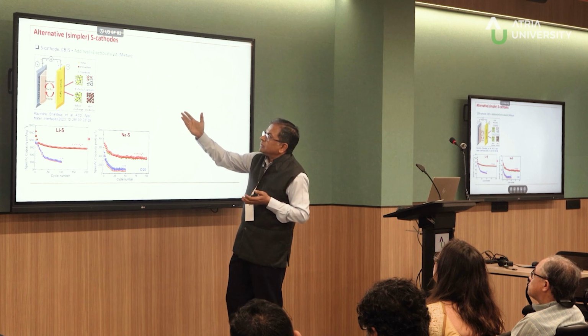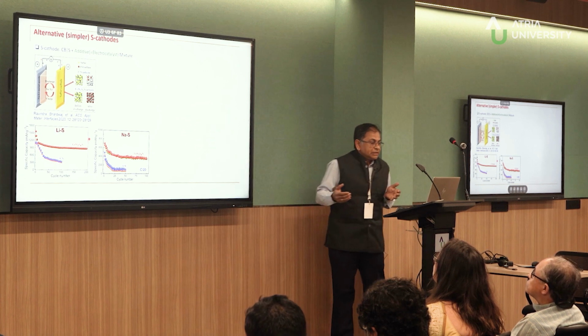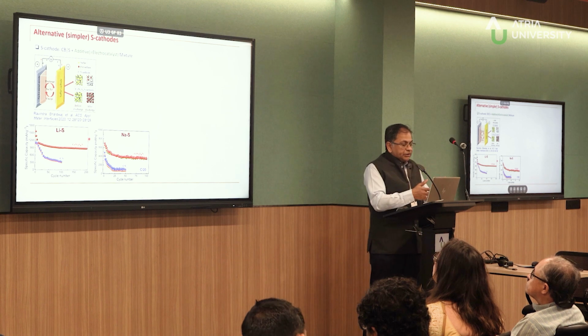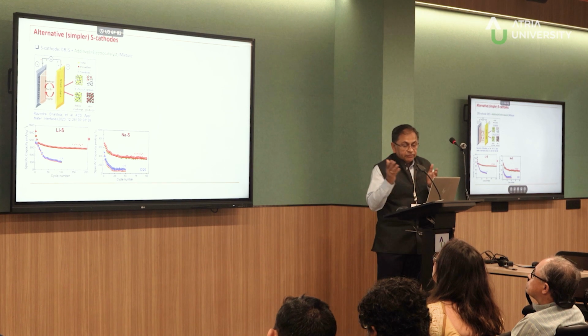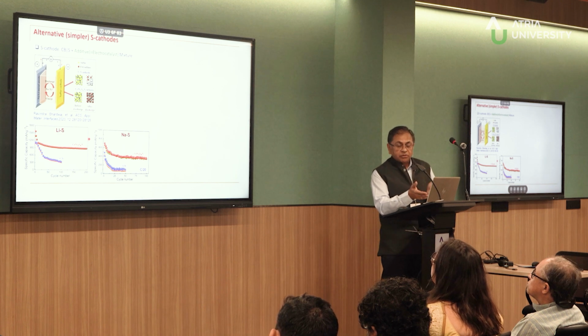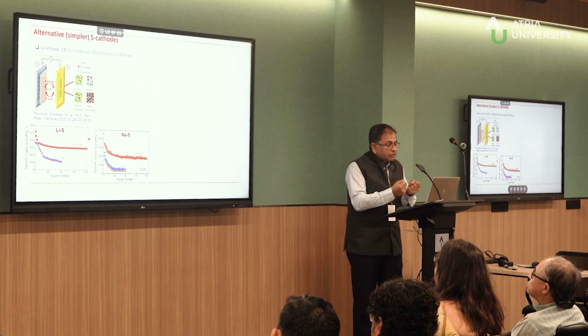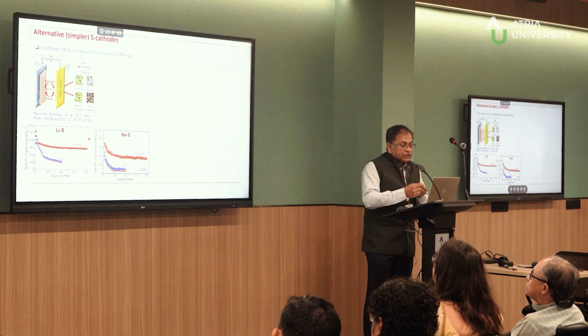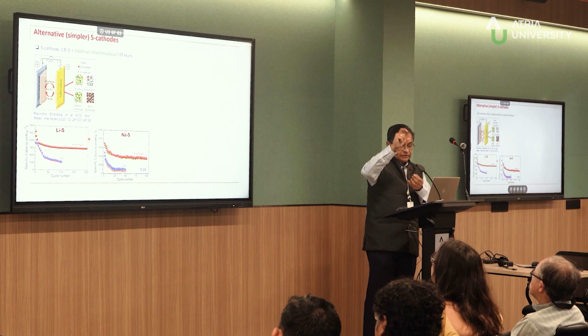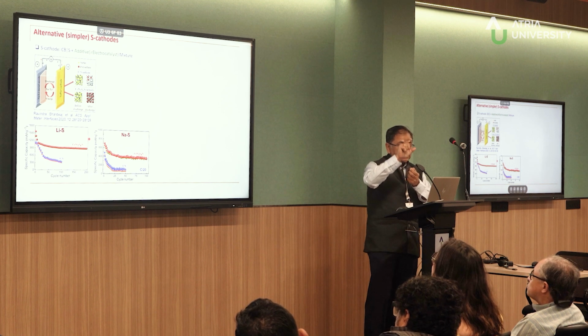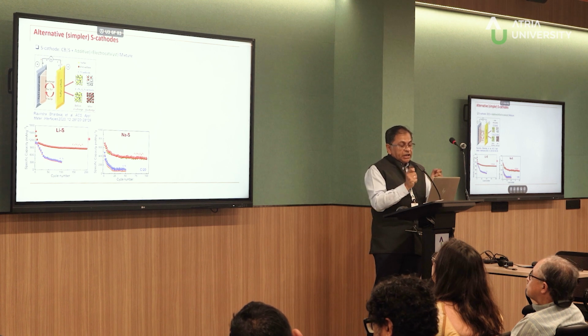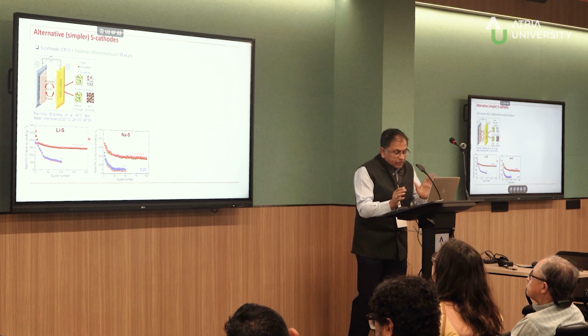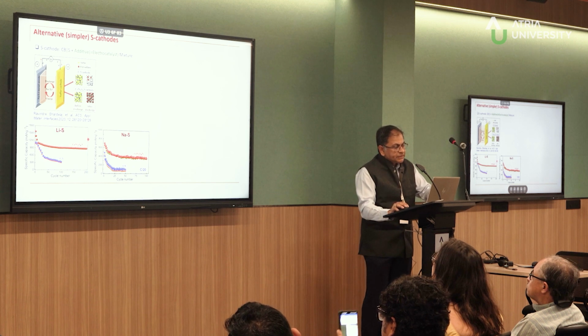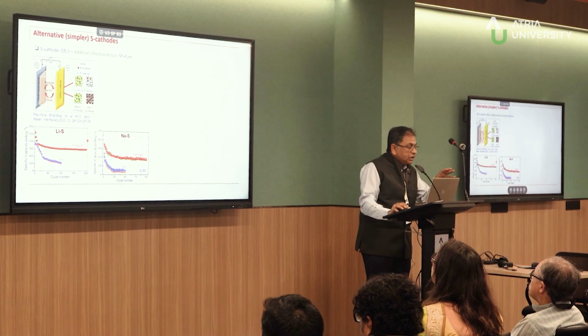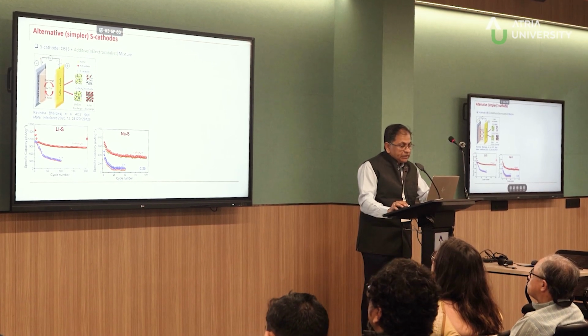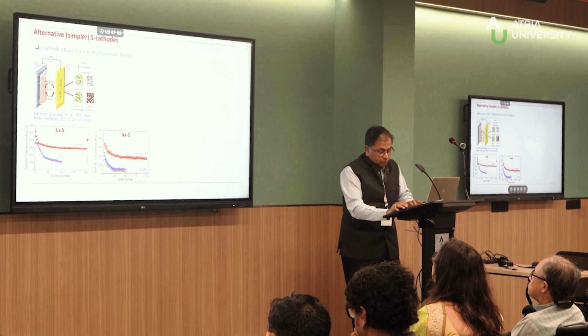You have cobalt, nickel. It's a great battery. At room temperature, you get good capacities, and even at 1C rates, you can also make a sodium sulfur battery with this. The cobalt nickel sulfide, the way it works is it is actually the sulfur of the polysulfide, which because of some residual charge, gets helped by the cobalt and nickel. Okay, so this is a kind of proof of concept that you can actually use electrocatalyst working in a sulfur cathode and doing the trapping and conversion mechanism.